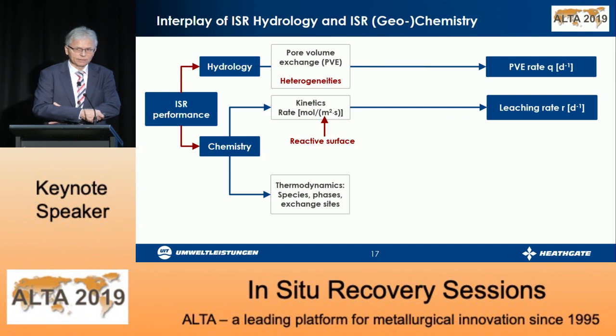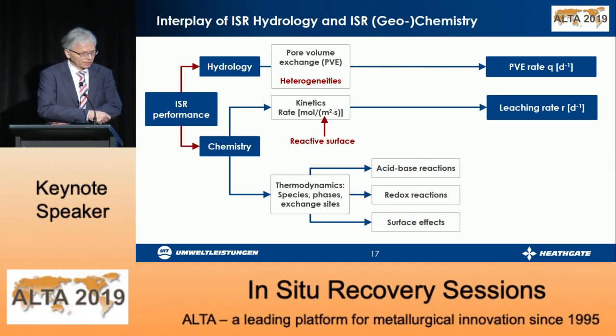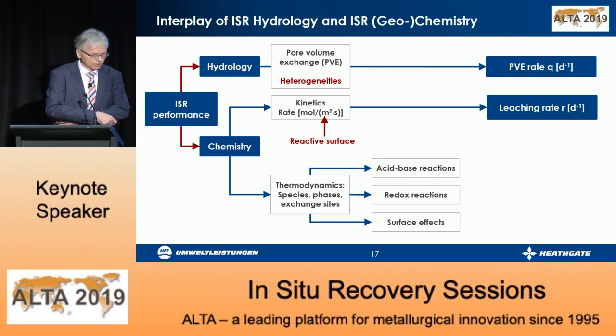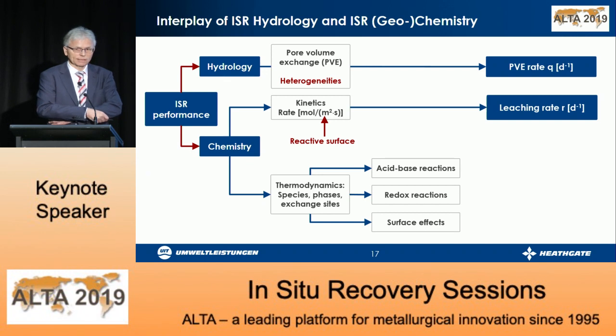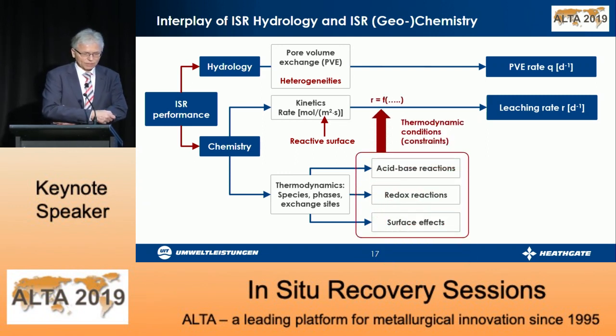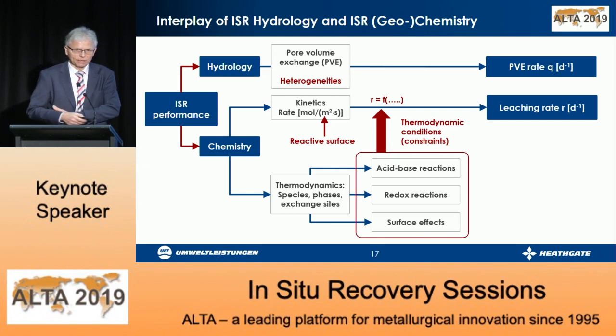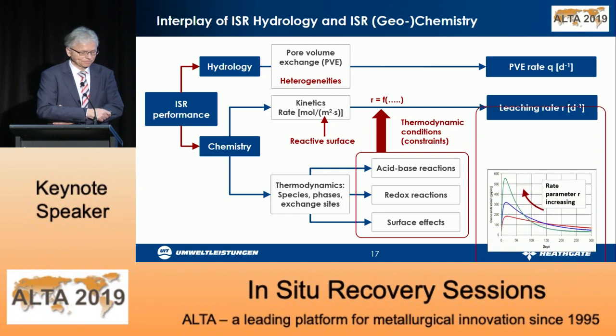The reactive surface, and that is what I'd like to point out, and what we have seen in the tomographic studies, is an important parameter for defining the leaching rate and finally for making an in situ recovery economic. Thermodynamic conditions for the various species, phases, and also the exchange sites, like on clays, result in acid-base reactions, redox reactions, and surface effects. And in this way, we sometimes have thermodynamic conditions or constraints impacting the leaching rates, and that's what you have to understand to avoid those.